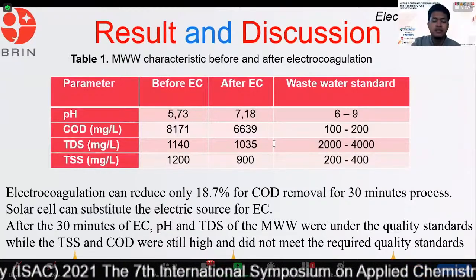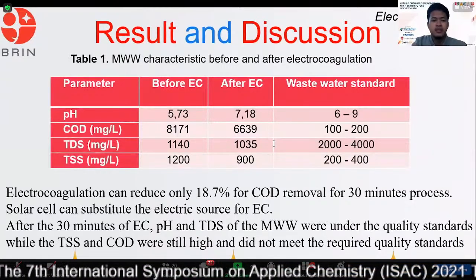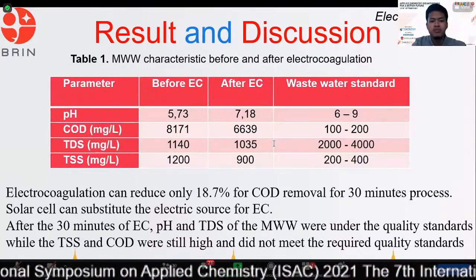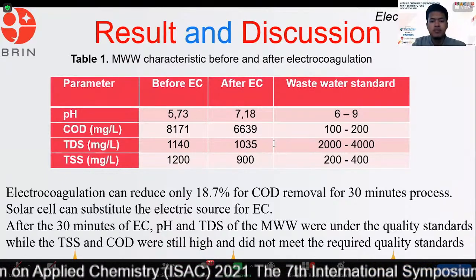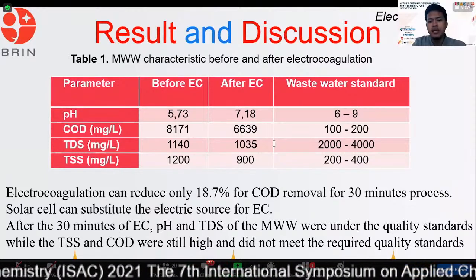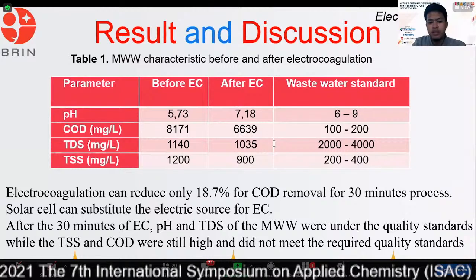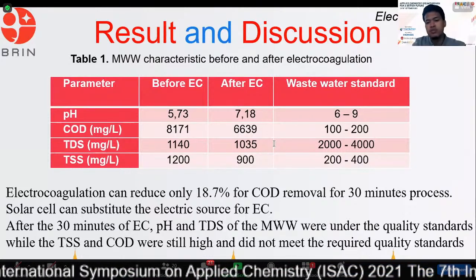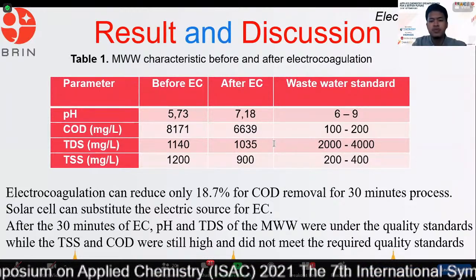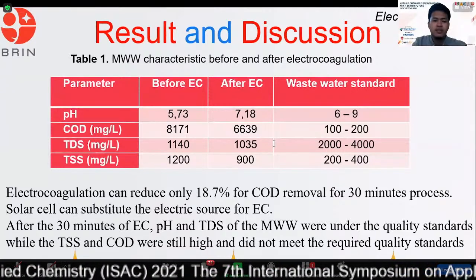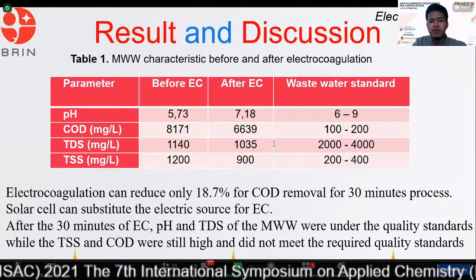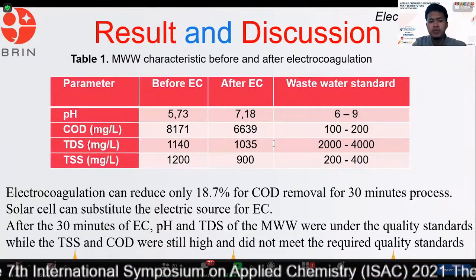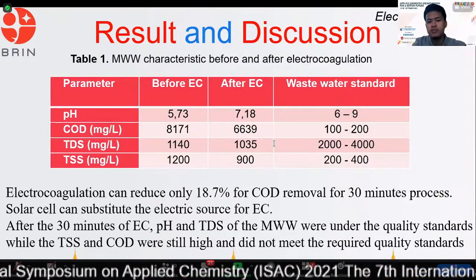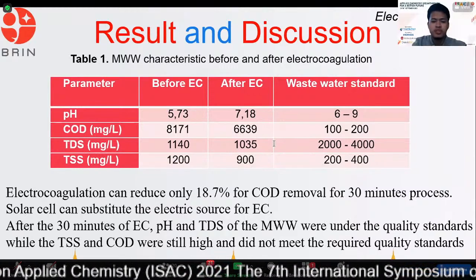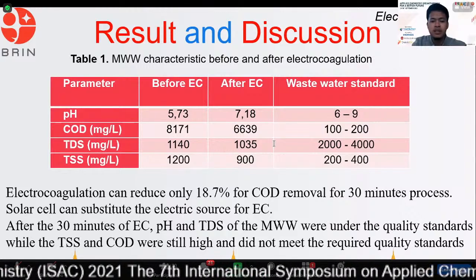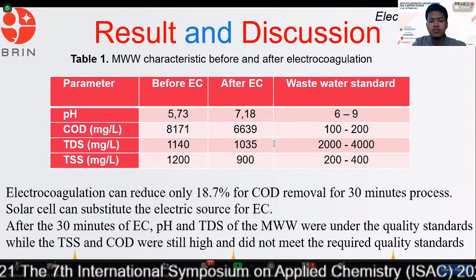Okay, this is my result. Can we see in the table? One, the composition of the MOCAF wastewater before treatment. The wastewater contains COD around 8,000, total dissolved solids around 1,000, and also total suspended solids around 1,200 ppm. The pH is around 5.7. You can see in the table that after electrocoagulation, the pH increased from 5 to 7. Also, electrocoagulation can reduce COD by up to 18% after the 30-minute process. In this process, we can see that the solar cell can substitute for the electric source for electrocoagulation.